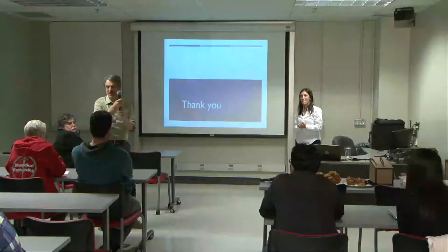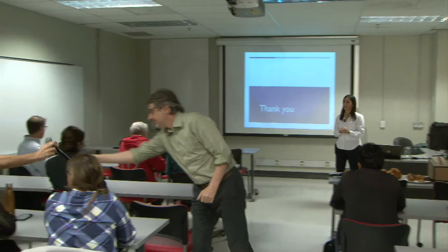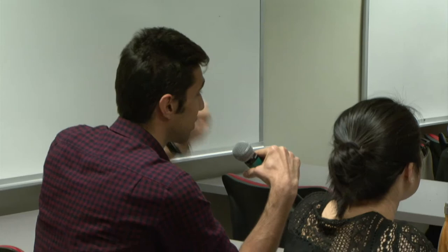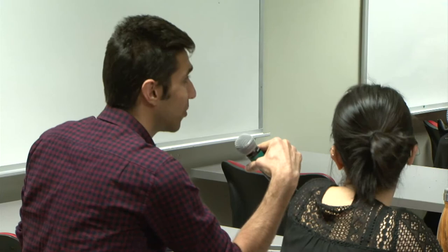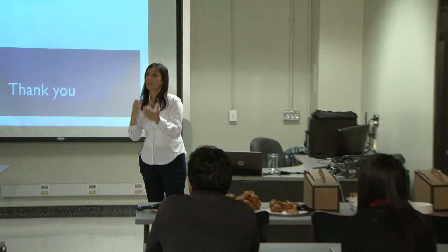Thank you for a very interesting talk. Questions? Audience: I didn't fully understand — the big picture is to immobilize enzymes on a silica nanoparticle, and you mix some chemicals together and they get immobilized. Is that correct? Yes, that's one of the approaches. And is this method mild compared to other immobilization methods I know? Yes, this is a good thing about this strategy. The synthesis is done at pH 8, at room temperature, ambient conditions, on top of your bench. You mix hydrolyzed TMOS or TEOS as a source of silica, phosphate buffer with your enzyme, and an aminated molecule — which could be a peptide, a polymer such as polyethyleneimine, really any molecule with a determined number of amino groups — and it polymerizes quickly.